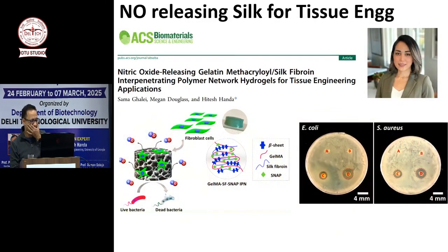Sama also did her PhD. She worked a lot on silk. We published multiple papers on silk. So she made this gelatin silk scaffold, NO releasing. Basically, this was her gel. It helped in antimicrobial properties. I purposely am showing you different types of studies, like this zone of inhibition study from those gels. And this gel was really good for tissue engineering type application because it helped cells adhere to the surface. And this network of silk made the gel very strong and not very fragile that will just break. So you made it stronger and antimicrobial and easy for cells to grow, so great for tissue engineering type applications.